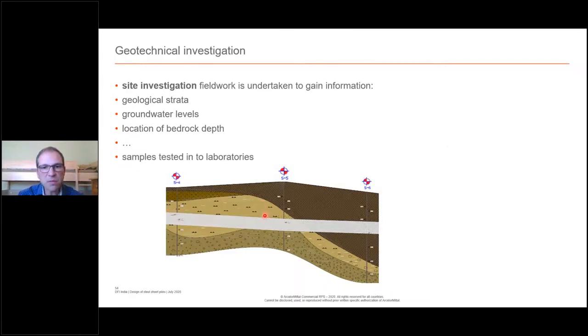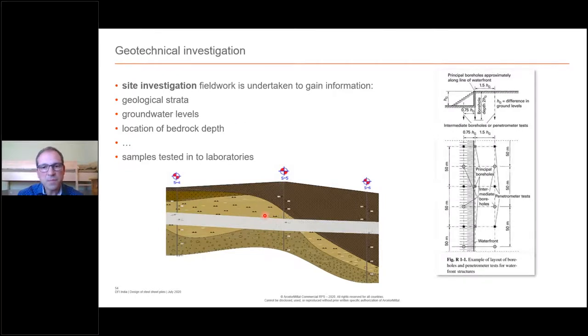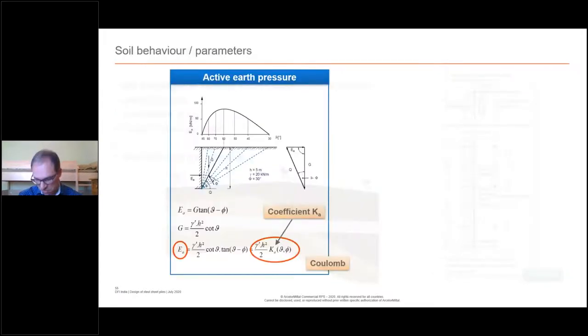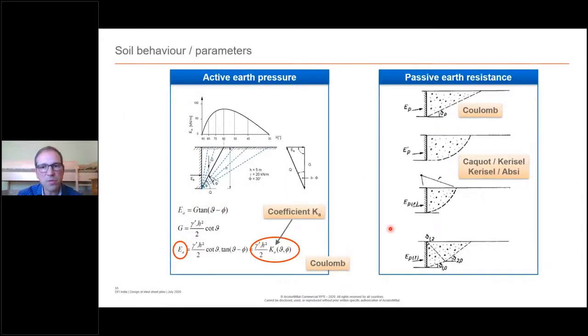So there is a recommendation from the German Waterfront Committee, which is called EAU, in which they suggest to make every 50 meters what they call principal boreholes, and in between also boreholes, not necessarily with the testing of the material, but at least to make sure that you get a feeling about the layers and also the material, and don't miss something like you could if you have only a few borings. But also to make these borings in front of the quay wall, at the center of the quay wall, and also behind, because this will give you a kind of a 3D information about the soil. And even though it's normal for the big projects, for smaller projects very often it is not done.